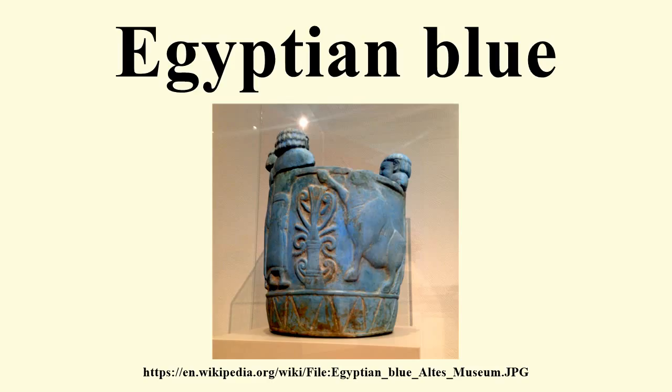During the reign of Thutmose III, the copper ore is replaced by the use of bronze filings. This has been established by the detection of a specific amount of tin oxide in Egyptian blue, which could only have resulted from the use of tin bronze scraps as the source of copper, which coincides with the time when bronze became widely available in ancient Egypt.